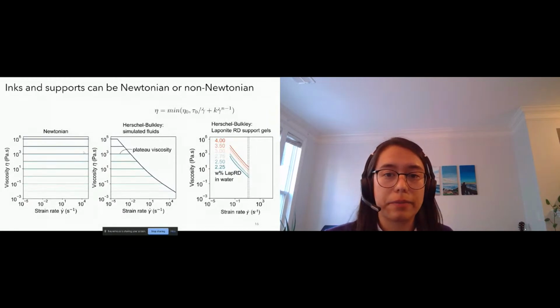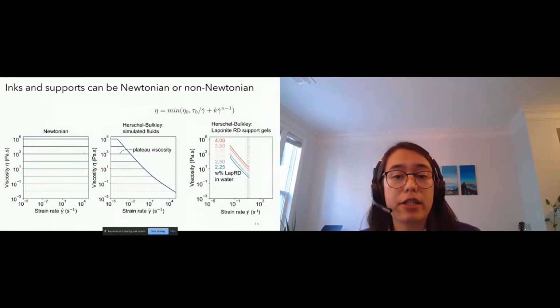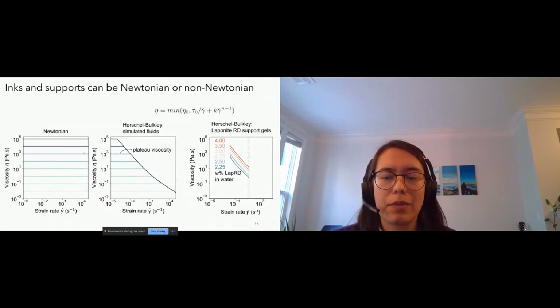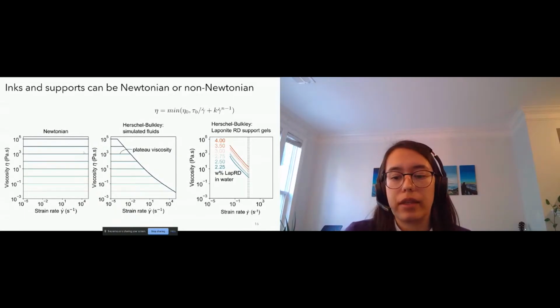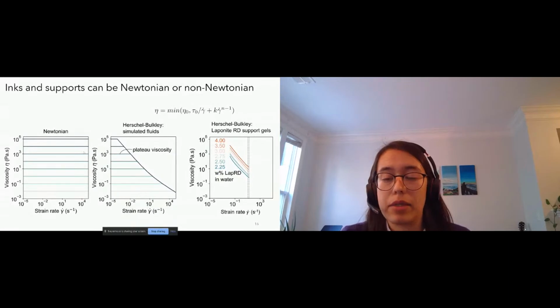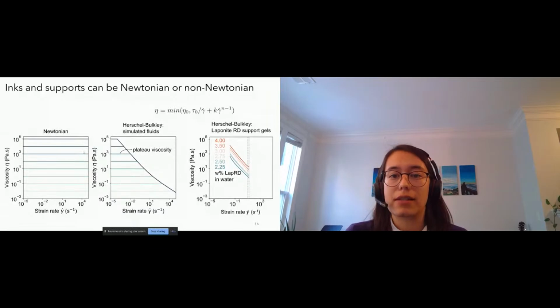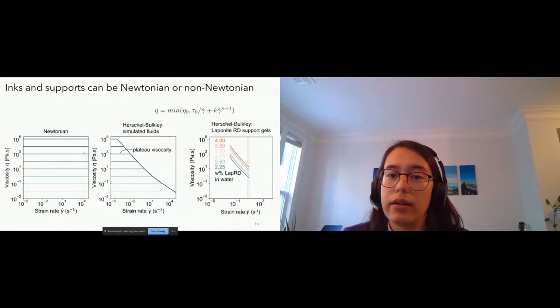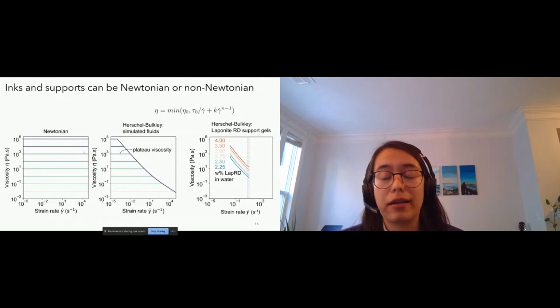just the effect of what the unyielded properties of the materials do to the structure of the filament. And then finally, for our experimental fluids, we're going to look at a variety of fluids, but generally they follow the same pattern, where they're shear thinning, but as you increase the amount of rheological modifier in that material, you're going to shift this entire shear thinning curve upwards, so increase its viscosity. So what I'm showing you here is laponite and water. So laponite is a fumed silicate, and it'll form these structures that will give it a yield stress and give it shear thinning properties.